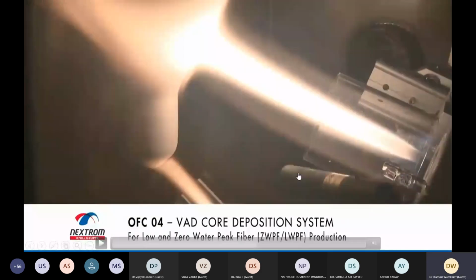See here, as you can see, there are two burners, right? So this is the inner burner, which has SiO2 plus GeO2, and it is surrounded by this, which is SiO2. Okay, so we find SiCl4 here, oxygen plus SiCl4. Here, oxygen plus SiCl4 plus GeCl4. So they form the core region. This forms the cladding region, the surrounding region. So at a time, this thing happens.